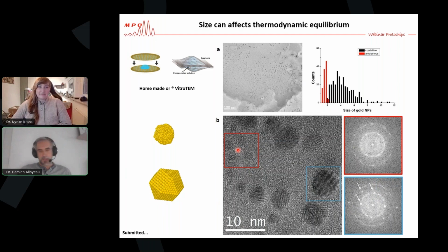Okay, we are working on it. So far we have published the result showing that we can improve the signal to noise ratio, but now we are working on this super resolution imaging, where we would have extremely noisy high resolution images, either in STEM or in TEM modes. And the idea is to use exactly the same strategy, work on numerically produced images to train the neural network and be able to improve the resolution and recover a noise-free high-resolution image, starting from extremely noisy high-resolution images. So that's on its way.